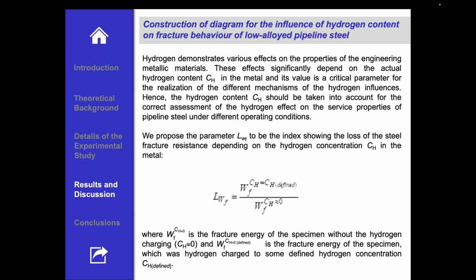And as the next step of our investigation, we constructed a diagram of the influence of hydrogen content on the fracture behavior of low alloy pipeline steel. We propose a parameter showing the loss of steel fracture resistance depending on hydrogen content in the metal. This parameter depends on the energy spent in fracture for the specimen without hydrogen charging and the energy spent after charging.